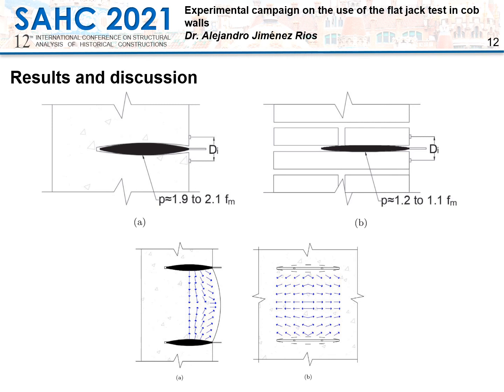When the pressure is increased by pumping oil in the system, the flat jacks start to deform. The deformation is not a uniform separation of the stainless steel plates, but more like a balloon inflation, with bigger deformation at the center of the flat jack and practically negligible deformation along its edges. The effect of this differential deformation is practically non-existent for small deformations, but becomes significant as deformations grow beyond the yielding point of the material, which actually happened while performing the double flat jack test of the cob wallets during this experimental campaign. The uneven deformation of the flat jacks caused the pressure to be transferred to the wallets in a non-uniform way. The actual load transfer to the wallets was more similar to a point load than to a uniformly distributed load.